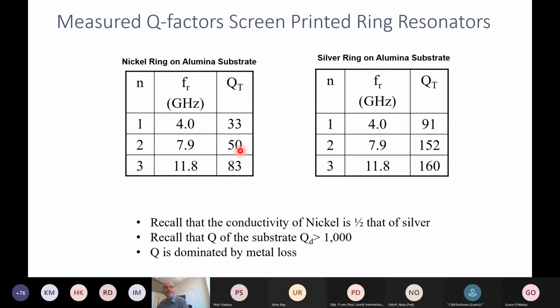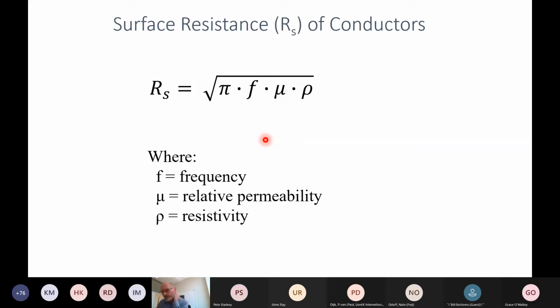The relationship is a little different at lower frequency. I'll get to that in a minute. But basically, you can see here we're about maybe 1/3 instead of the 1/2. And that was of interest to the folks making the multi-layer ceramic capacitors, because there's another thing that affects this surface resistance of a metal.